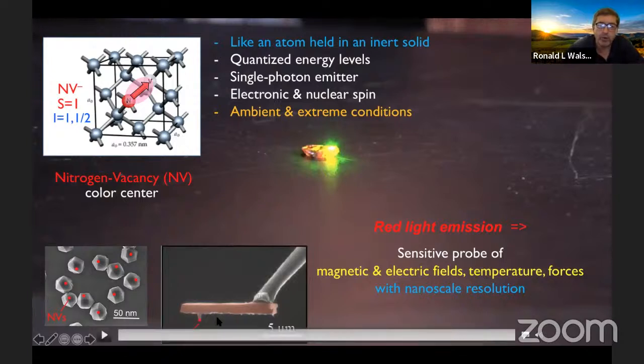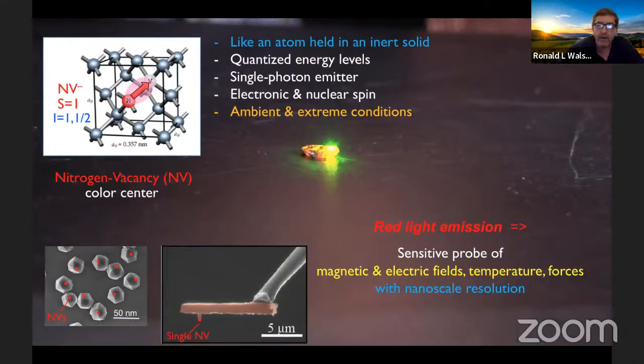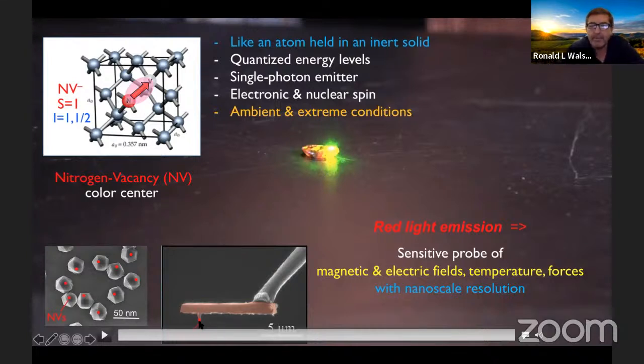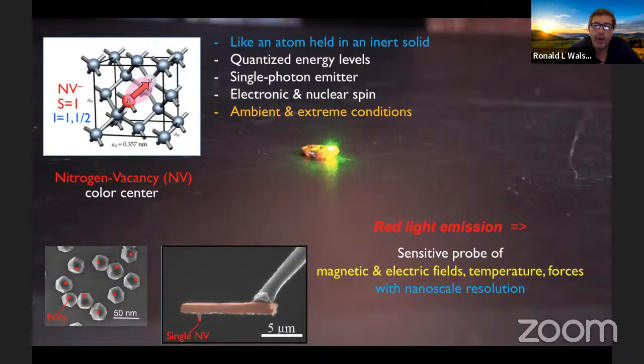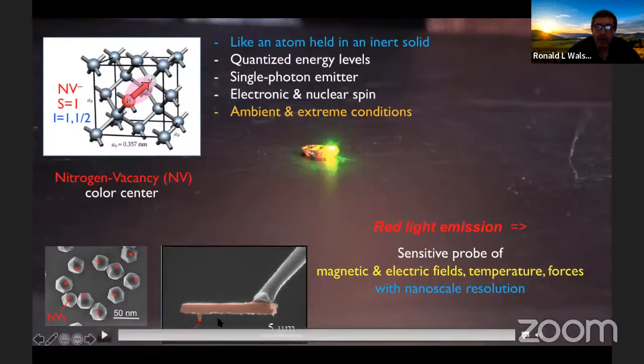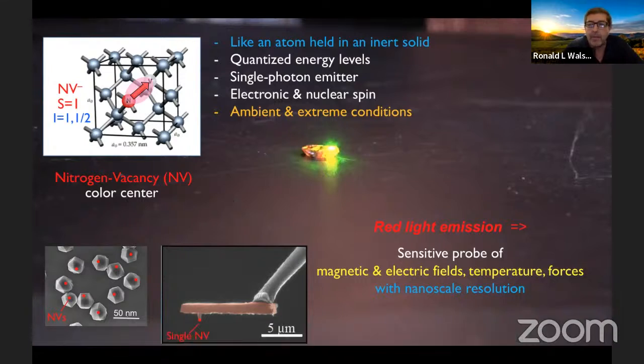Sometimes you might grow a small nanodiamond pillar, as shown here, that maybe is 100 or 200 nanometers long, and have a single NV just a few nanometers away from the end of the tip, and then attach this nanopillar to an object which is controlled by piezos to be able to scan over the surface of some object of interest. And you can make a scanning diamond atomic force microscope and, for example, map the magnetic or electric fields coming from some sample that's right below and be able to do extremely high spatial resolution mapping of magnetic fields and electric fields coming from graphene or some multiferroic or some other material of interest, superconductors, et cetera. And there's a wide range of research using that kind of tool.